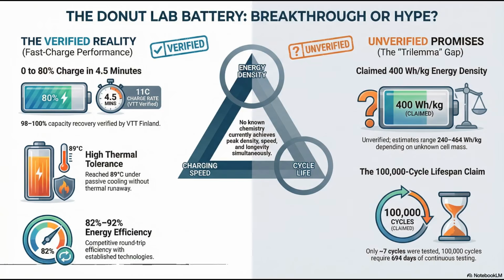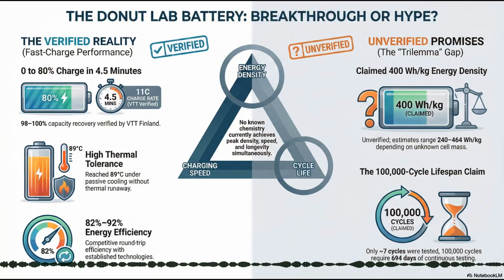Sure, hot is good for solid-state conductivity, but operating at 90 degrees leaves you with absolutely zero margin for error. Right. If your absolute safety cutoff is 90 and you are operating at 89... You are one minor sensor glitch away from potential failure. Now, to be fair, Donut Lab claims no thermal runaway, meaning even if it fails, it won't catch fire. Which implies the electrolyte is non-flammable. Likely a ceramic or a high-temp polymer, yes. But we haven't seen the nail penetration or crush testing data to actually prove that safety claim yet. We are just taking their word for it.